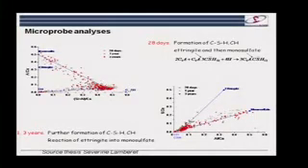And as we go on to later samples, you see that the ettringite starts to decrease, and the amount of monosulfate intermixed now starts to increase. But we still have this cluster that represents our CSH composition, and we can use that cluster to get quite a good idea of the average composition of our CSH. So our average CSH has a calcium to silicon ratio here, and a sulfur to calcium ratio, etc.